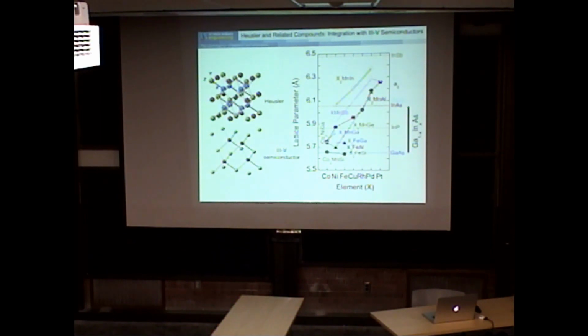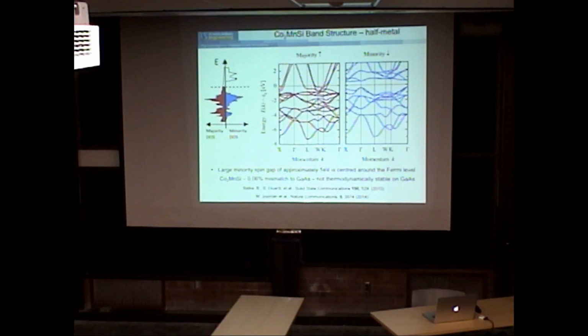I don't see it there, but it should be. It's actually close to gallium arsenide. So here now is the cobalt manganese silicon band diagram. This is calculated, not measured. You can see here, the majority of spins is metallic, the minority of spins is a semiconductor. And the gap here is normally of the order of 1 eV.